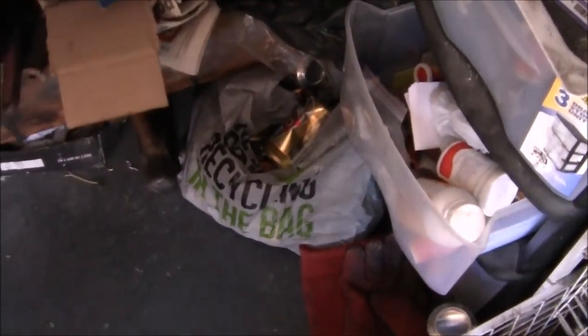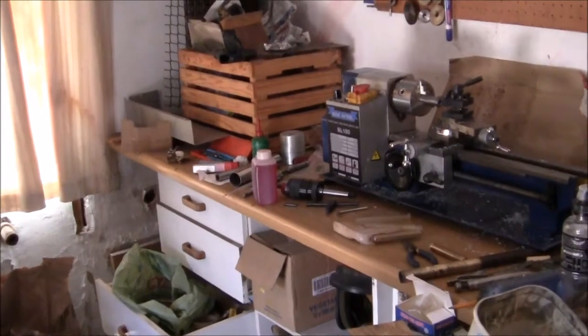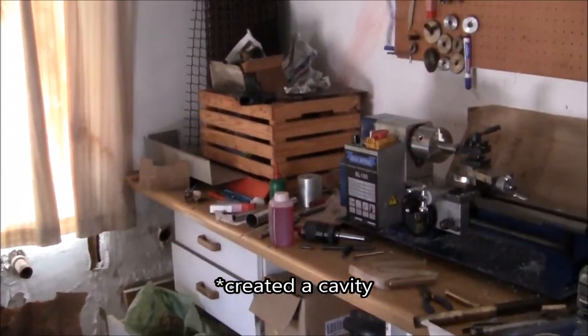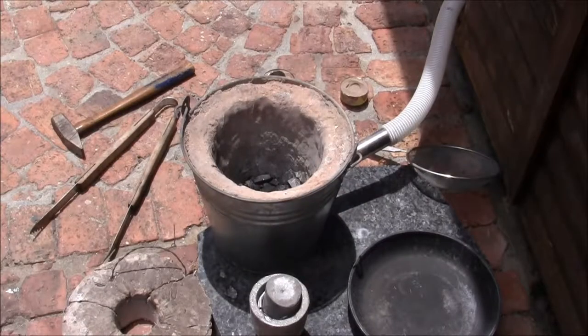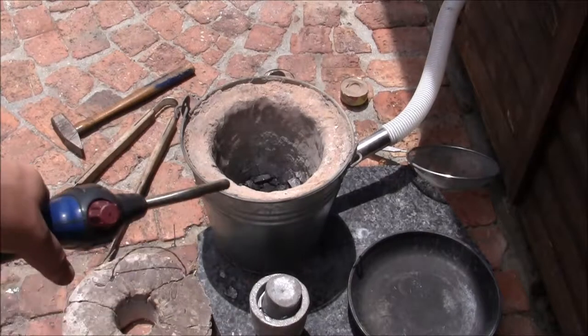I get the aluminium from scraps from whatever I can find, and I also have bags of cans that I've been collecting over time — I melt those down to get my metal. What I've been doing so far is melting it down, pouring it, and then putting it on my lathe. You can see some of the cylinders I've cast. You can see a dent in the top — that's from when I tried to cool it down with water and it shrank so much it dented severely. I've learned my lesson and now I let it cool down slowly.